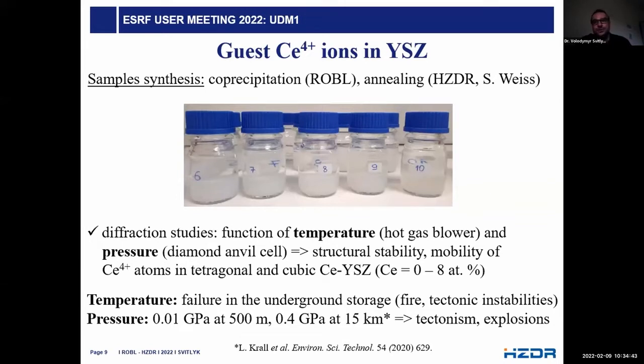Well, pressure, for the high pressure community, is quite low, from 0.01 GPa to a maximum of 0.4 GPa. But we apply this pressure for hundreds of thousands of years, even millions of years. And you cannot exclude that it can be increased during this time due to some possible tectonic instabilities, explosions. And so we apply higher pressures to push these systems to extremes and to induce possible structural evolutions, transformations, which could occur over this long time of storage.